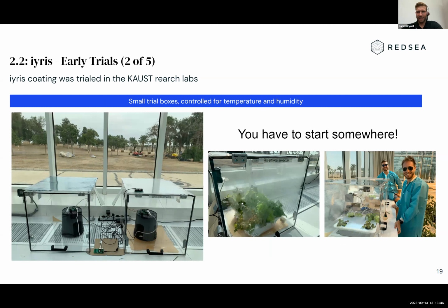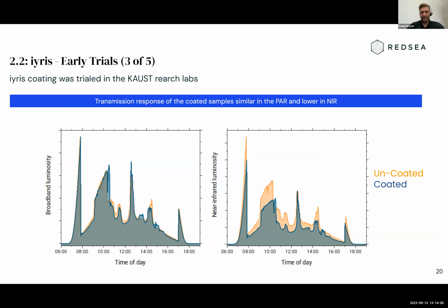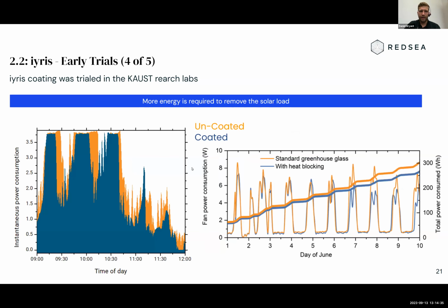So it's funny to be looking back now from where we came, but we definitely had to start somewhere. And it's a good acid test that we always do now, even in the company: make something on a bench, see if it works in principle. What we saw was these spiky looking graphs are because there was shading throughout the day, but as you go from morning to night, you can see that your broadband luminosity, roughly equating to your PAR, remains similar between a coated and a non-coated small test greenhouse, and your near infrared luminosity was decreased. And this was promising enough for us to take these materials forward even more. On the mini greenhouses, it proves the fundamental effect.